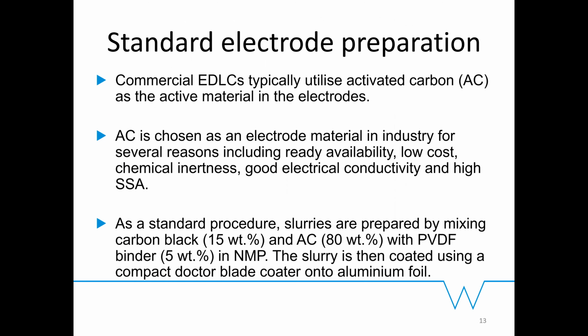Usually for supercapacitor testing in industries, activated carbon is the most common material that is used, usually because it's quite available, it's inert, and it has very high specific surface area. And usually these electrodes are commonly prepared in the industry via the doctor blade method, by slurry casting, using NMP as a solvent. And the ratios of the materials are usually this, like carbon black and activated carbon, PVDF, and so on. So what we are trying to do in our research is compare this standard slurry cast method against the electrophoretic method, and seeing if any improvement can be seen, which can be recommended for the industries for supercapacitors.